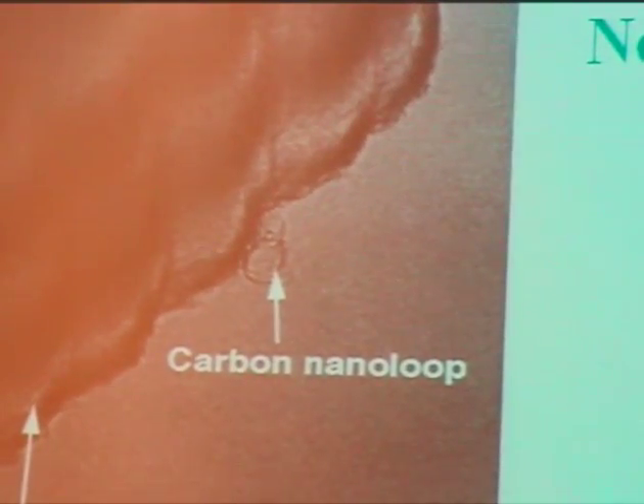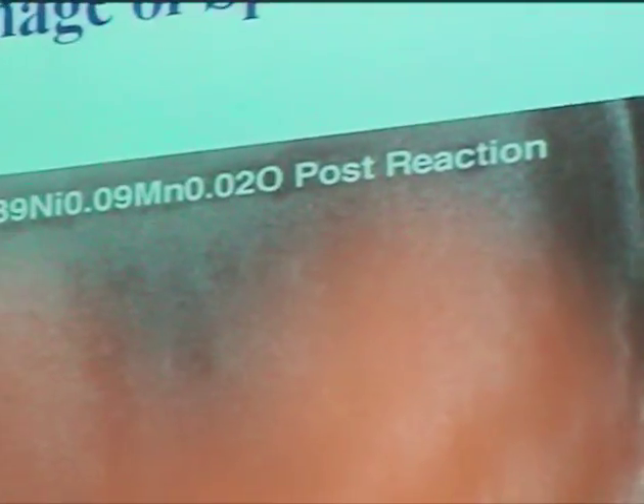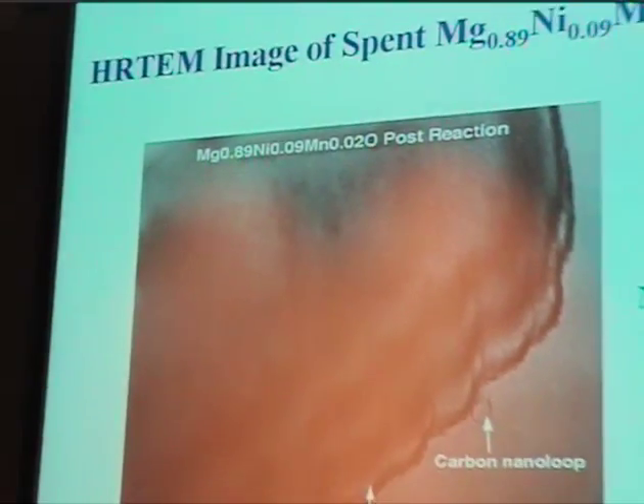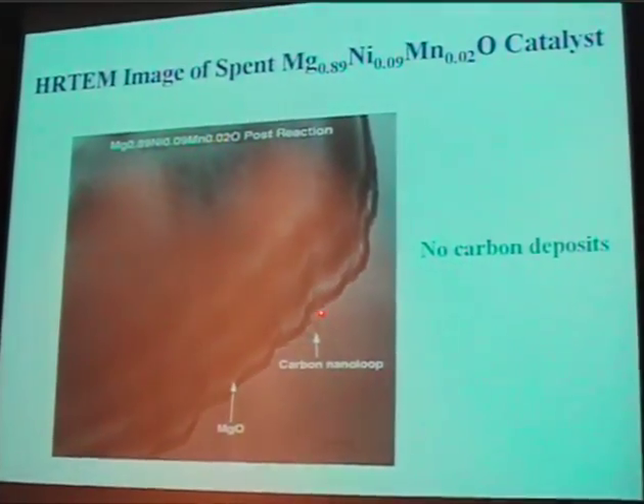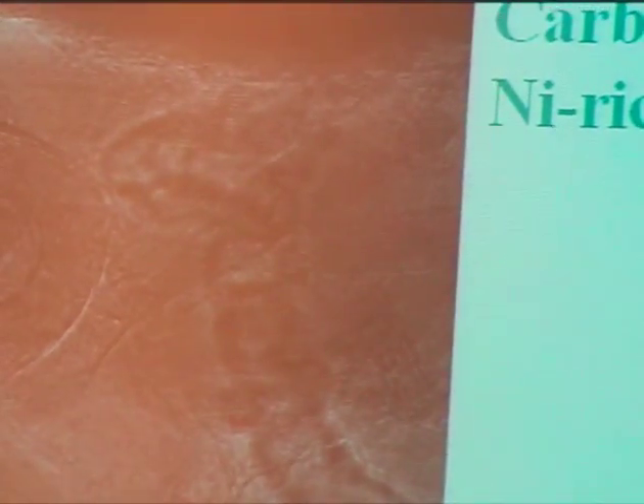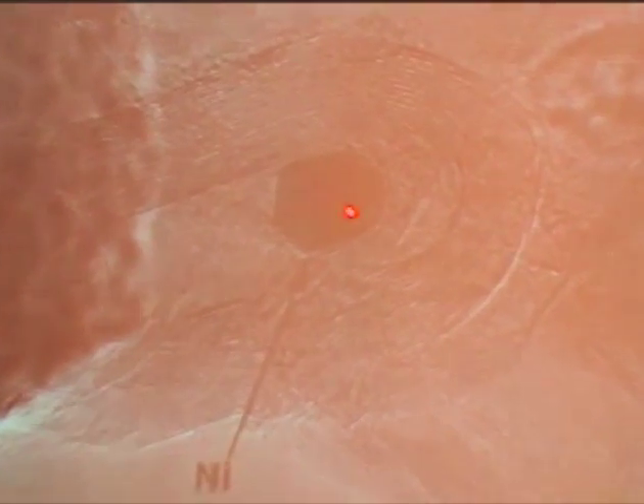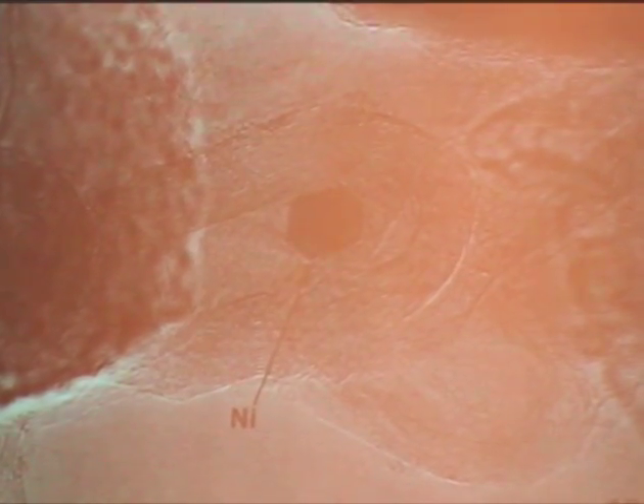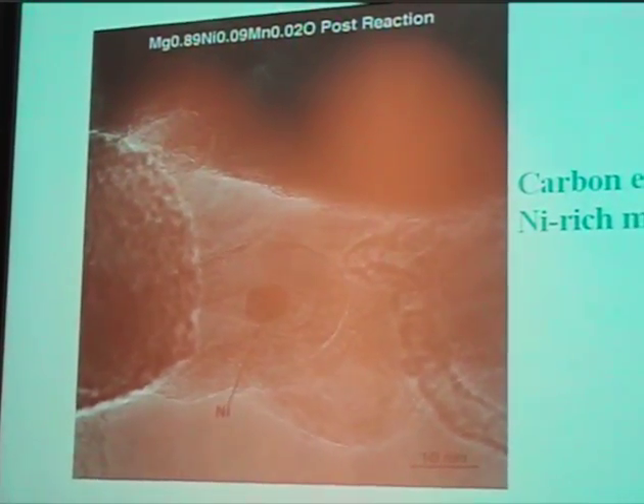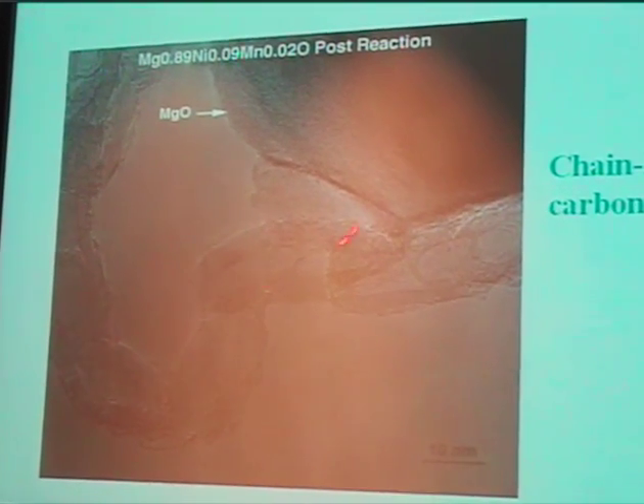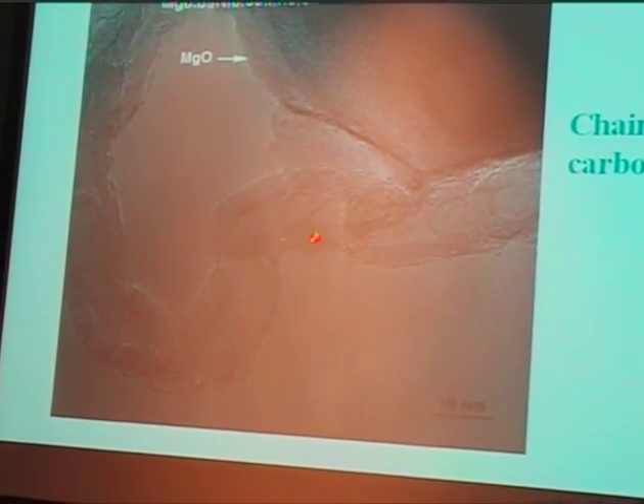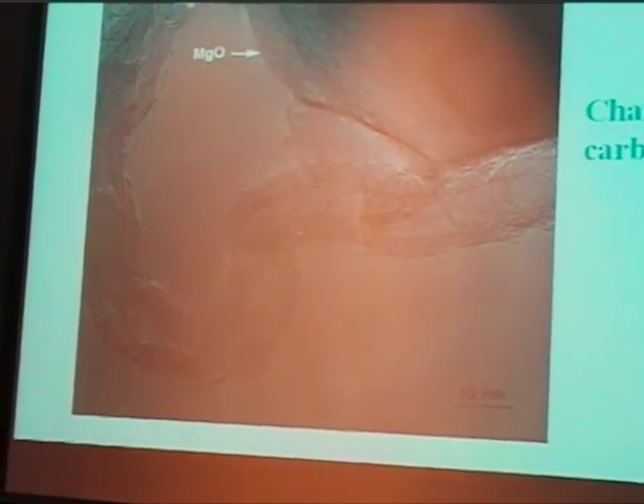Here we have the manganese promoted catalyst, and we don't see any detectable carbon when we do the thermogravimetric analysis, but under inspection, if you look around, you can see little things like carbon nanotubes showing up, but nothing that is really problematic in terms of operation. And every once in a while you'll see a nickel particle, although it's a lot smaller than the ones that you saw earlier, on the order of 10 nanometers, in the encapsulation of the carbon after reaction. And here's just another picture. It's just kind of interesting how we were seeing this carbonaceous chain-like configuration there.